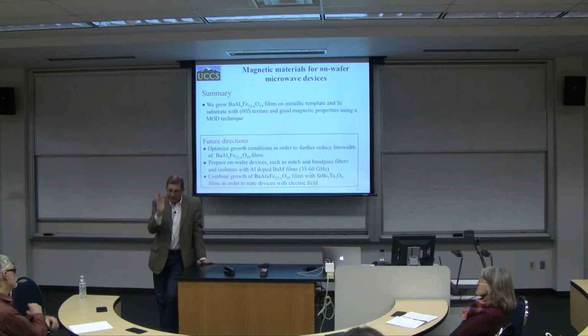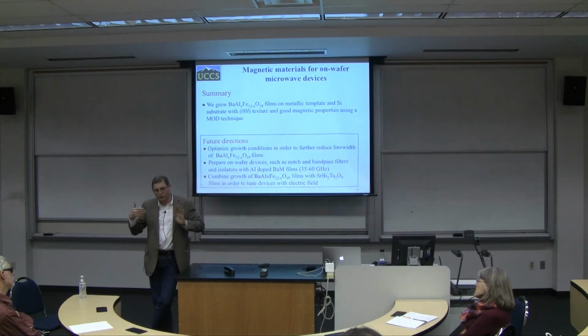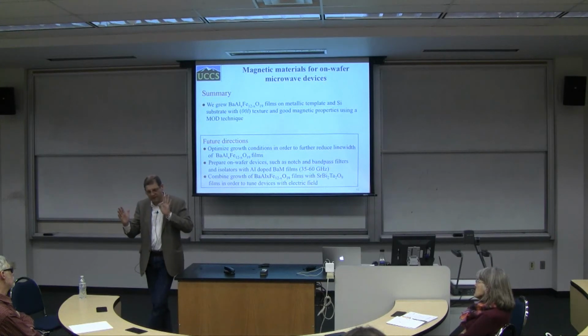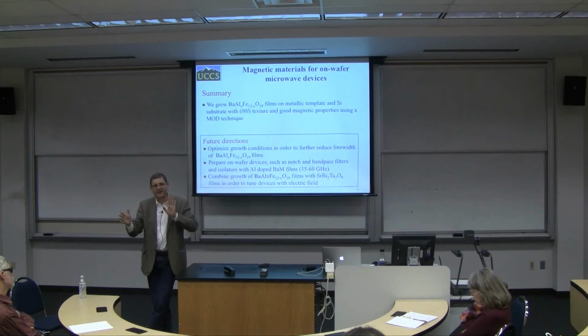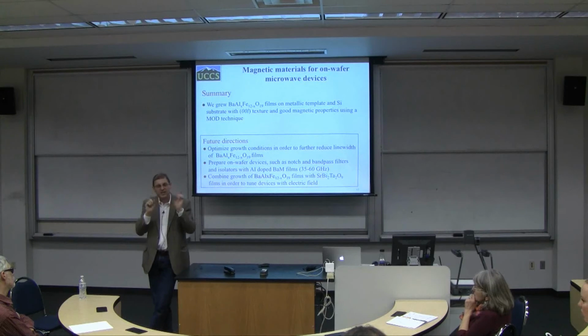And so this light propagates, changes the plane of polarization, and what you measure in your system, you have a polarizer and analyzer. In other words, you are measuring in a cross-polarized system, where one polarizer is in this direction, and the second is perpendicular to it. And therefore, you see any small changes in the polarization of the light.